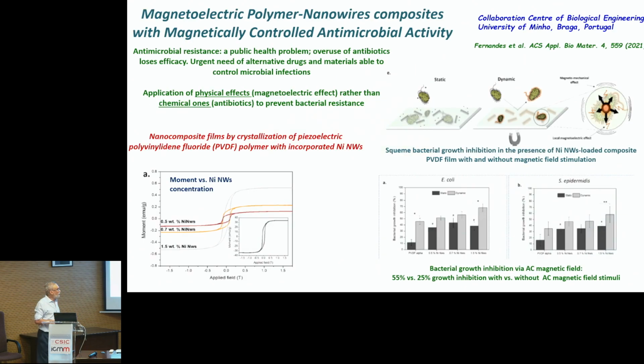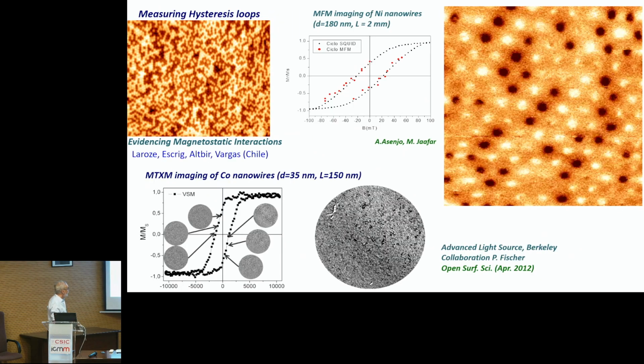This also I would like to mention, although I am not an expert at all, in a collaboration with Margarida Fernandes from the University of Braga. They prepare magnetoelectric polymer nanowire composites with magnetically controlled antimicrobial activity. They were interested in developing new alternatives to chemical products, because the overuse of antibiotics loses the efficacy of these antibiotics. So an alternative is to use this magnetoelectric effect in this composite of piezoelectric polyvinylidene fluoride PVDF polymer with incorporated nanowires. So they observe that the inhibition of growth of bacteria is very important using this magnetic activity of the nickel nanowires inside the polymer. Now I would like to show more specific work in the laboratory.